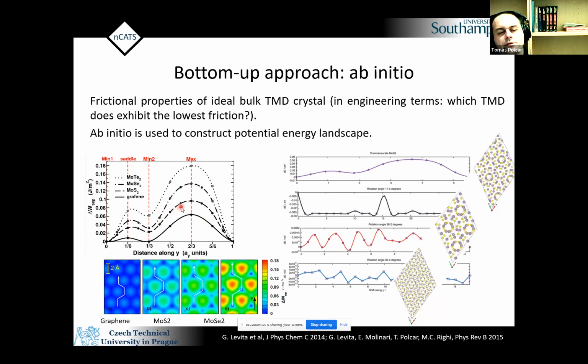So this is something that I would call ideal friction, or let's say static friction, because we can really compare materials and say which one is more likely to move when I apply the force. We cannot really get friction or coefficient of friction from this simulation. Of course, you can say that this is the case when we have a commensurate surface, like graphene to graphene commensurate one. What about rotating them and getting much lower friction?